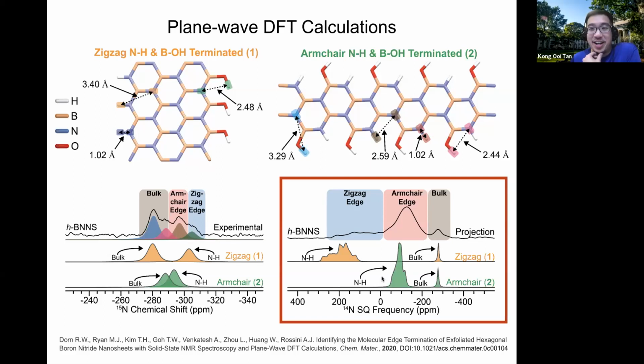Will they be better at higher field? Well, at higher field, I guess the resolution should be more or less the same. The second order powder patterns will scale inversely with the applied field, exactly, as will the second order chemical shift or quadrupole induced shift. So I think the resolution would stay the same actually.